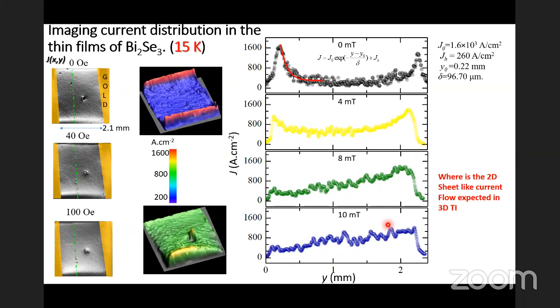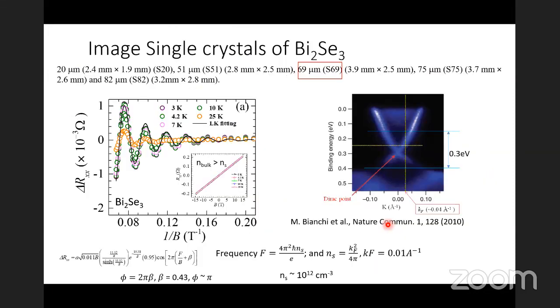Now let us go over to imaging the single crystals. We looked at a variety of single crystals, but I will just tell you about the results on a 69 micron thick single crystal of Bi2Se3. You can see the nice dHvA oscillations which correspond to the surface states. You can do a fitting, and you can show that the surface state is actually sitting below in the bulk gap of the material. So these are actually conduction from the surface states in Bi2Se3. This is as far as the basic characterization of the crystal is concerned.